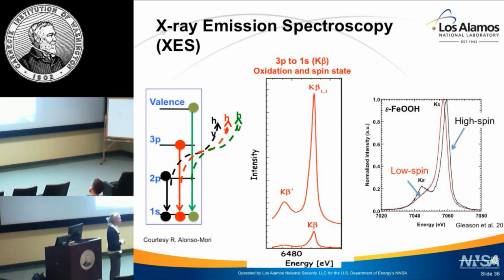So we looked at the spin transition in this material. The typical pattern you would expect, coming from synchrotron-based experience, is a K beta and a K beta prime. When the transition takes place, the K beta prime peak actually disappears. So we hope to see in our shock compression data some sort of K beta prime peak diminish or go away completely. That's what we expect to see. Here's a picture of the spectrometer itself.